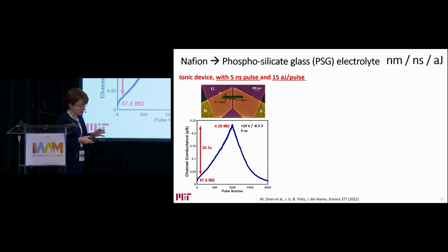But there is no good proton conductor at room temperature, that's period. But there are a few candidates that we could work with that become just enough proton conductor for us to work with. So the first one here is phosphorus-doped silicate glass, abbreviated as PSG. So this is pretty much silica that the CMOS field knows how to work with.